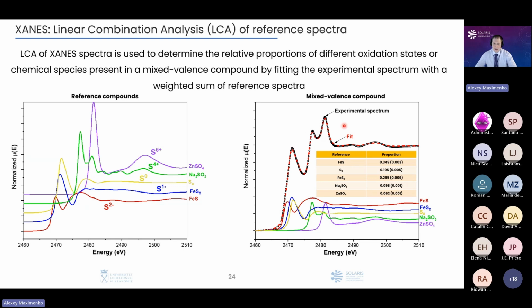This is a sulfur K-edge spectrum of a mixed valence compound. It allows me to understand how many atoms of sulfur I have in sulfide form, how much of them is in pure sulfur, and for example, how much of them in the sulfate. And that's how the analysis could be made using the linear combination fitting.